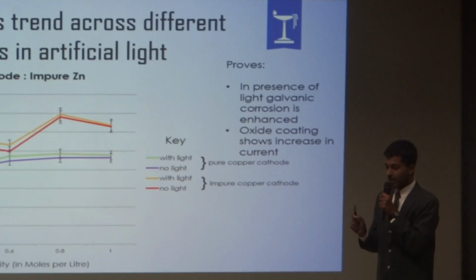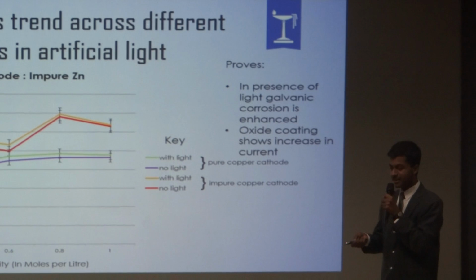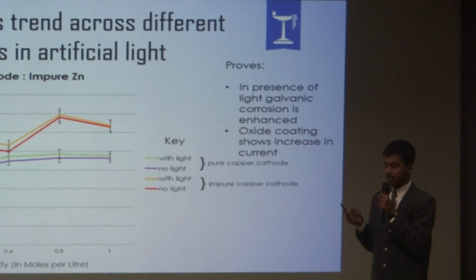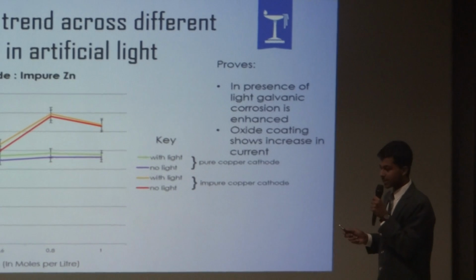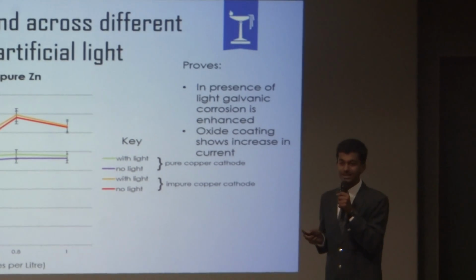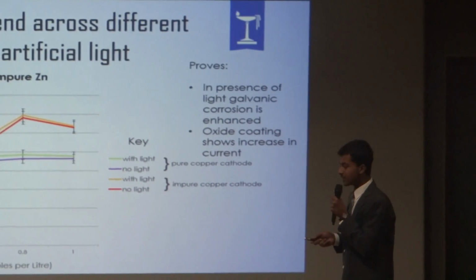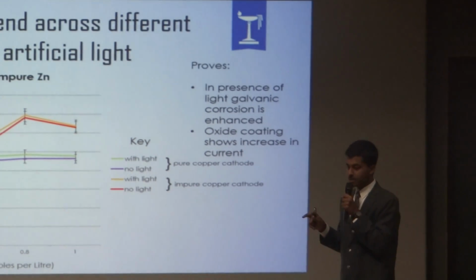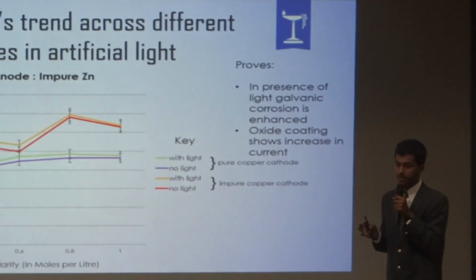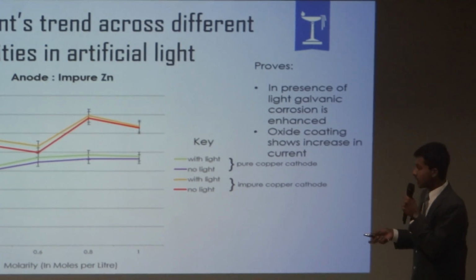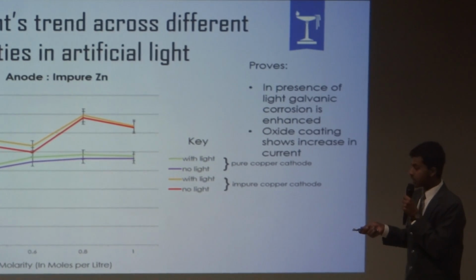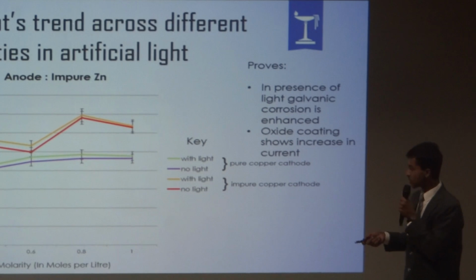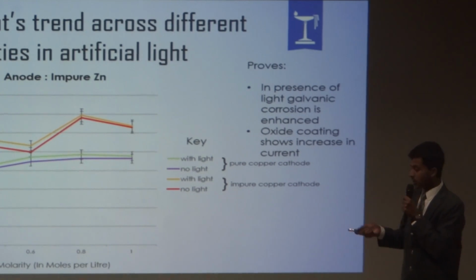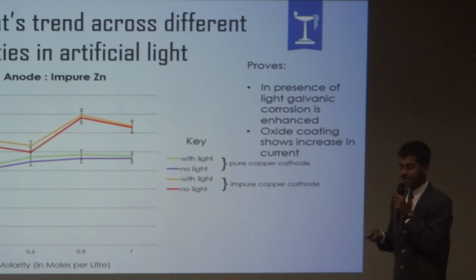the sunlight was actually not increasing the current in a photoelectrochemical way, but there was another phenomenon which was taking place, and this phenomenon is known as galvanic corrosion. Now what galvanic corrosion is, when two dissimilar metals with different electrode potentials are taken in a salt solution, the one metal, the anode, which has a lower electrode potential, tends to corrode because of the electrochemical reaction which is taking place. So after all these slides, afterwards we will conclude that